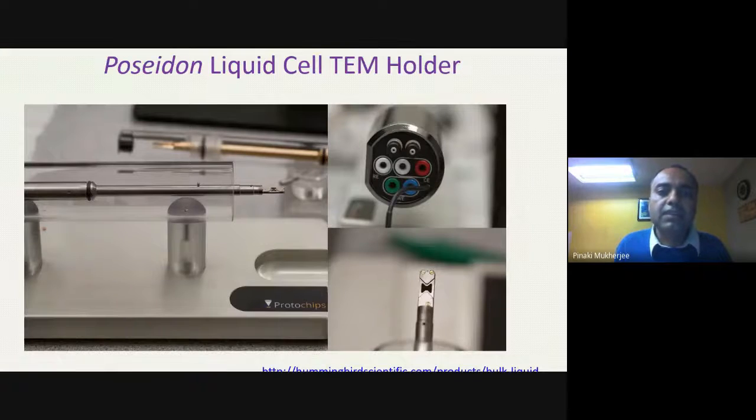And we have a liquid cell TEM holder where we can see samples in their liquid environment, and we can actually form a pseudo cell inside a TEM, and we can see when we are charging or discharging, and how the cathode side reacts, if there is any bulging, and so on. In this technique, the resolution is maximum at nanoscale, not atomic scale.